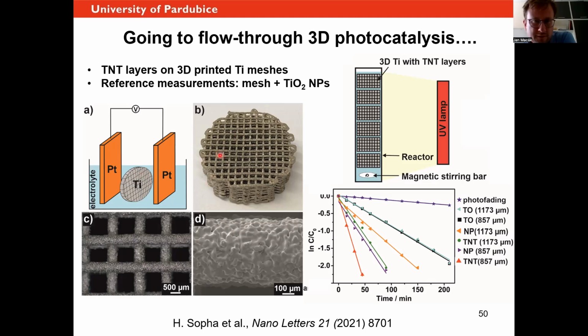We had to use some specific approach, which is called bipolar anodization. It is a wireless anodization process that, believe or not, it's possible, because it would be very difficult to connect these meshes somehow to have really uniform placement towards the electrode. So we use this double electrode and bipolar assembly here, and it is possible by doing this assembly to grow nanotubes also on these very meshes. And you can then take these anodized meshes, put them in a reactor in a stack, and have a really proper UV illuminated reactor.